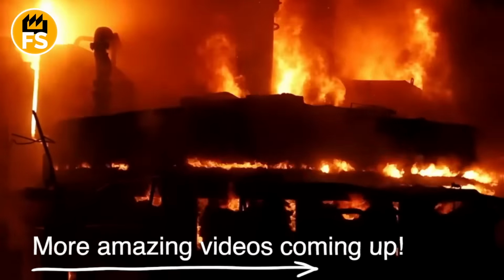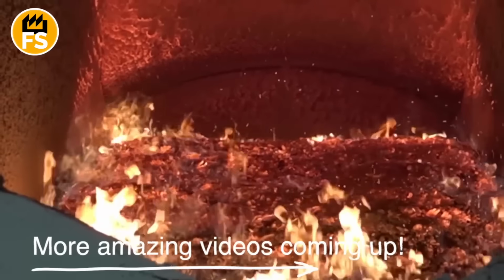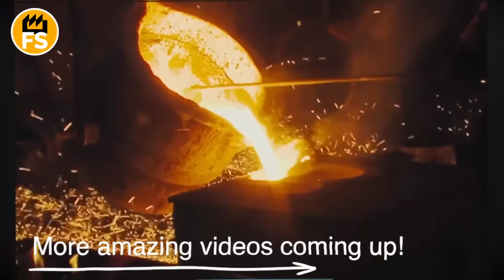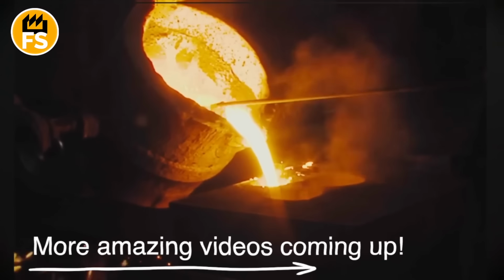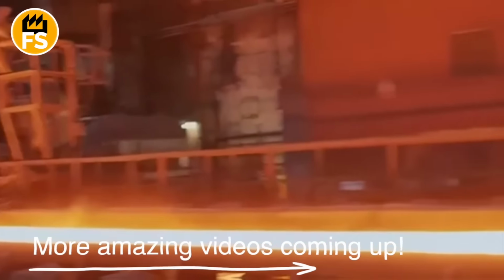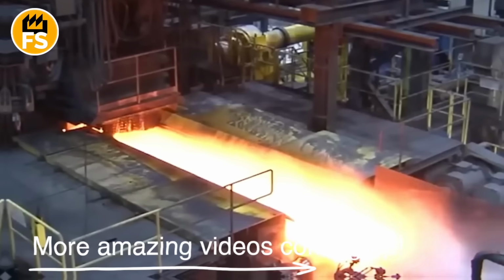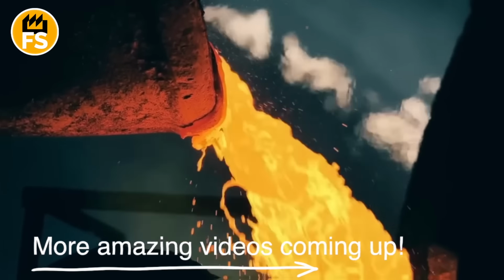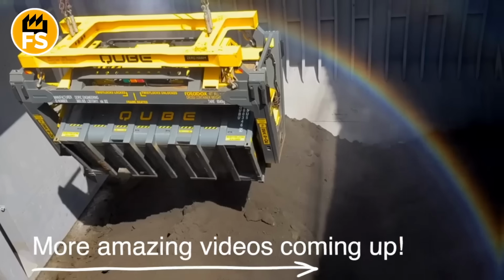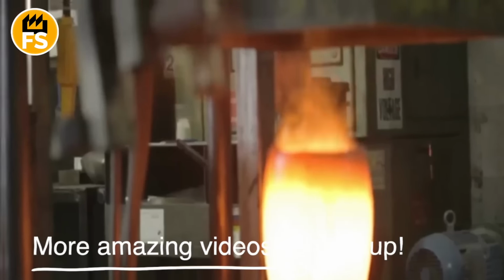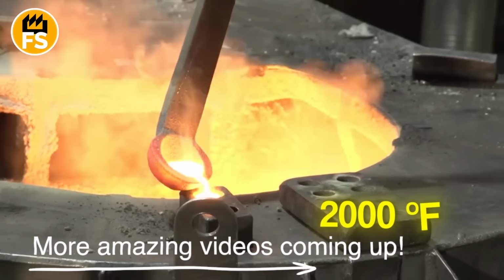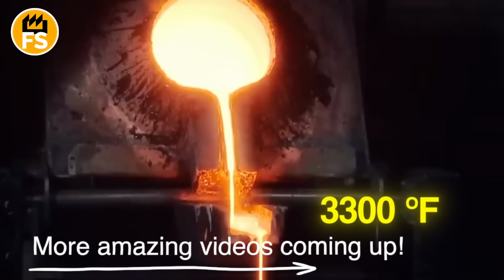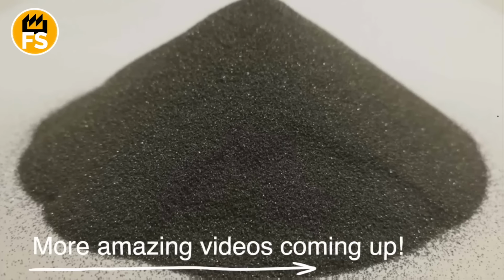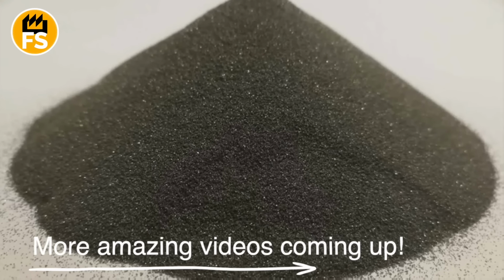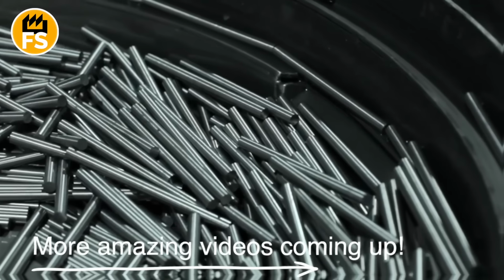The concentrate is then processed at metallurgical plants to extract pure tungsten. It's a complex chemical process that can involve alkaline leaching, precipitation of ammonium paratungstate, and its subsequent roasting to produce tungsten oxide. The tungsten oxide is then reduced to metallic tungsten by heating it in a hydrogen atmosphere at temperatures ranging from 2000 to 3300 degrees Fahrenheit. The result is a fine tungsten powder, which forms the foundation for all subsequent products.